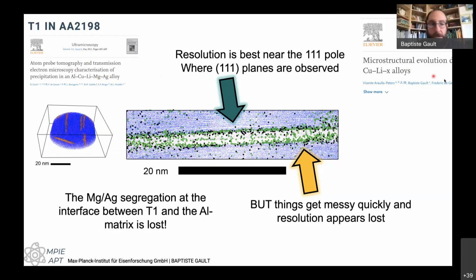And then we looked at similar alloys a bit further, a few years later, and we looked at these alloys with the set of 111 planes positioned in the center of the detector in a way that we could actually maximize the spatial resolution. And if you do this, you can see that effectively silver and magnesium, so silver is black and magnesium is green, are segregated right there at the interface between the matrix and the precipitate. But as you start to go away from where the planes are visible, where things are a bit more messy, it's almost impossible to tell that there is this segregation. So we made a mistake. We've learned a bit since then.